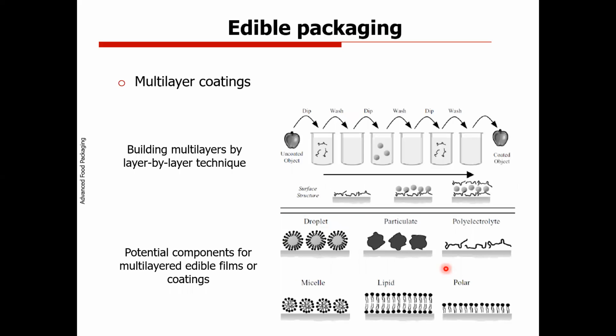When you talk about edible packaging, what I showed before is a simple coating process. So we are dipping or spraying, but there are other possibilities. You can produce multi-layer coatings. If you remember the layer-by-layer technology on a substrate, like glass or paper or another kind of substrate, we can also do the same to fruits and vegetables and other kinds of products. We tested mostly all foods, and you can see here how it goes. You have your food and you make this immersion process: wash, dip, wash. So we make the immersion in a polymer, wash, another polymer, wash, another polymer, and then you have your coated object, or in this case, fruit.